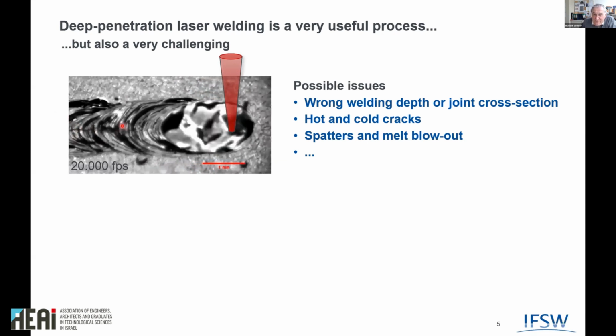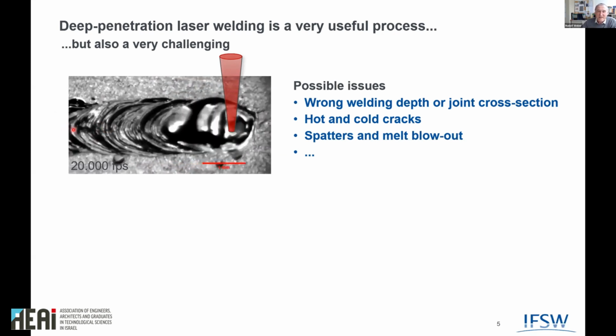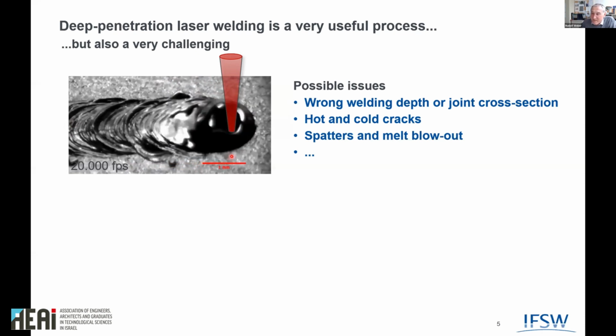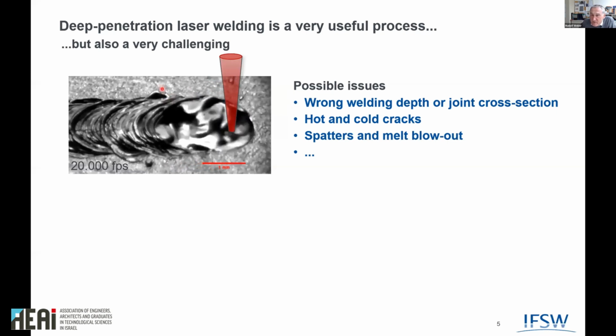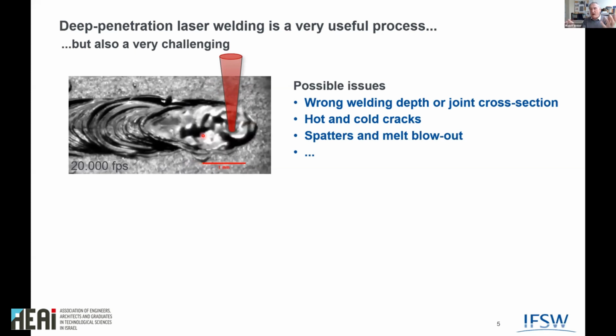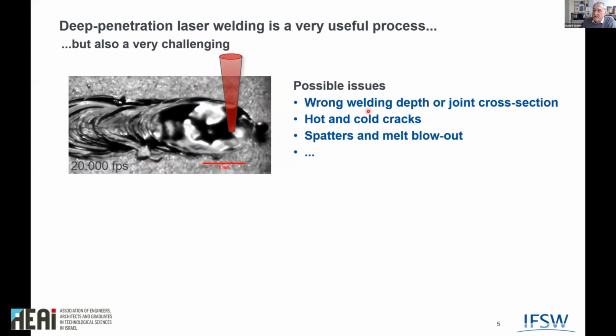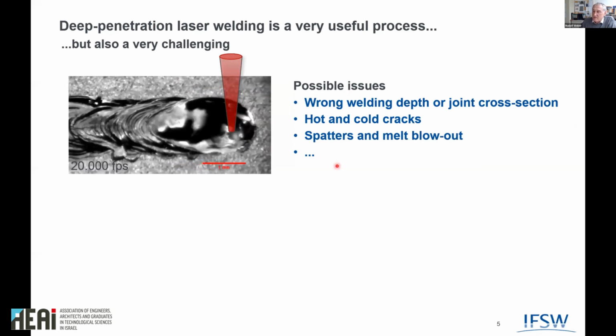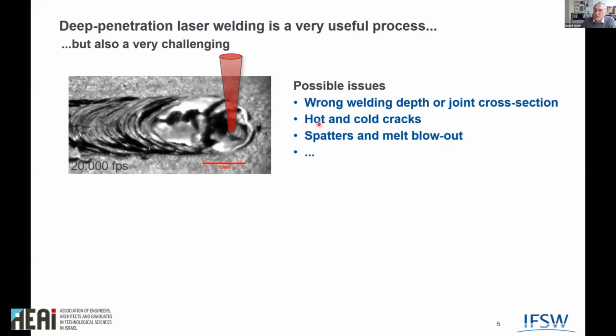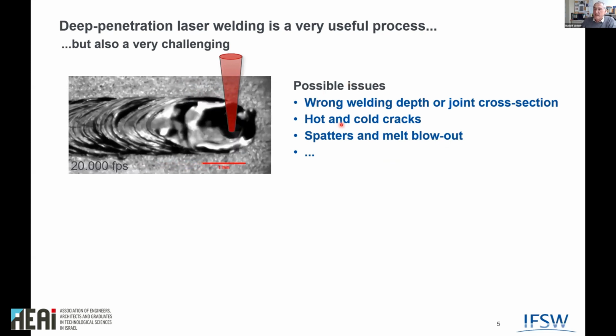The other thing, if you look a little bit closer, you can see that there is a very nice crack building up at the end of the weld. Of course, usually you don't want to have such a crack. And also you can see there are big and small spatters emerging from this bubbling liquid, which is the metal surface. And in my talk, this is more or less the contents of my talk. I want to say a few words about these three topics,